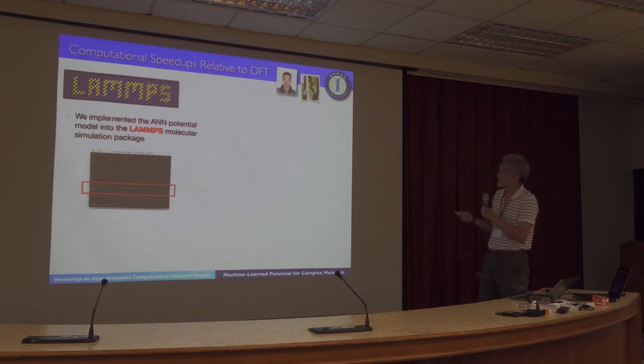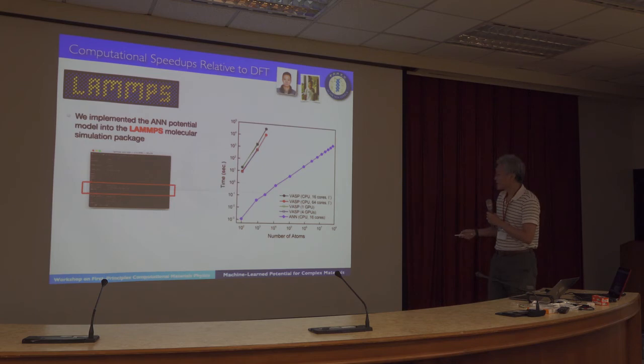So what we did is that we implemented the neural network potential models into LAMMPS, the molecular dynamics simulation package. And we just introduced a new concept here. This work was done by my postdoc and also another postdoc. And here is the benchmark. This is the number of atoms. We start from 100 all the way to 0.1 billion atoms. And this is the time required for each step. These are from VASP using CPU and also from GPU, 1 GPU, 4 GPU. And this purple line is from CPU, using just 16 cores.